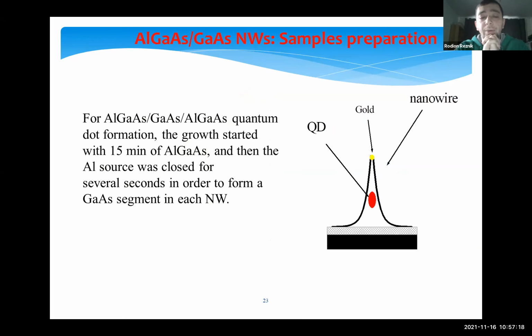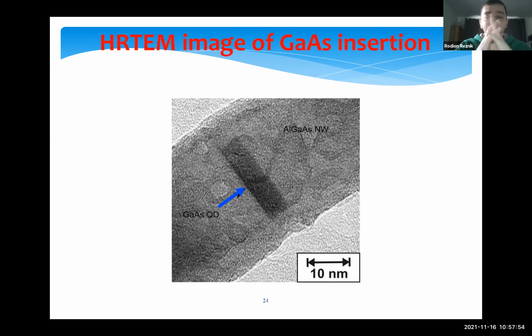The next step, we formed aluminium gallium arsenide nanowires with gallium arsenide quantum dots on silicon substrate, just by closing the aluminium shutter for some seconds. The principal scheme of such a structure is presented here. So this is the gold particle at the top of the nanowires, and the quantum dot inside the aluminium gallium arsenide nanowires. After the growth, we didn't find any difference in morphological parameters of nanowires, but in TEM we can see these gallium arsenide quantum dots inside aluminium gallium arsenide nanowires, which for sure confirms the gallium arsenide quantum dot formation inside nanowires.